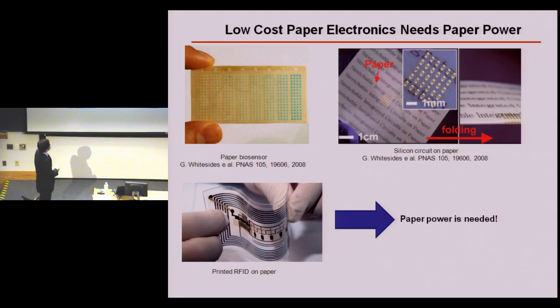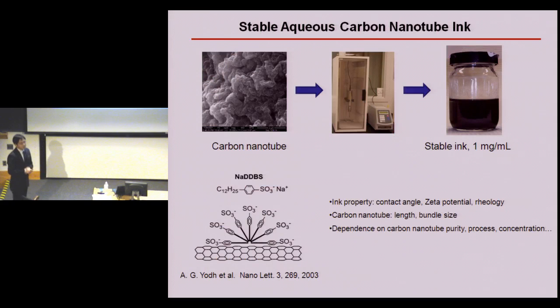So with these two motivations, I started to make a highly conductive paper. When I joined Professor Yi Cui's group at Stanford University, I proposed this idea, and it has actually become a very exciting field. The way we make paper conductive is based on carbon nanotube ink. So this is a carbon nanotube powder, and with the help of surfactant, basically we have a surfactant wrap around the carbon nanotubes.